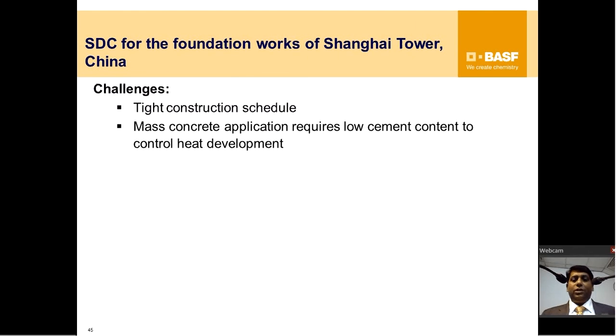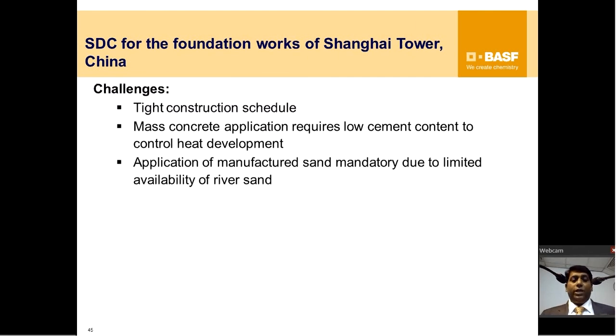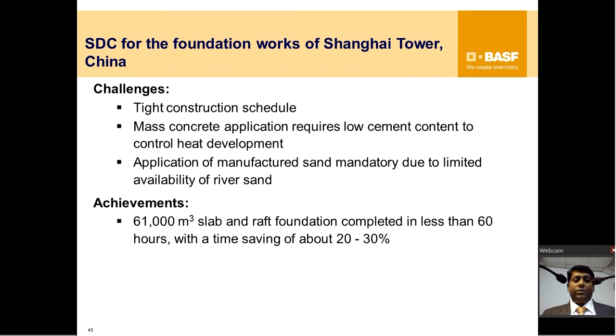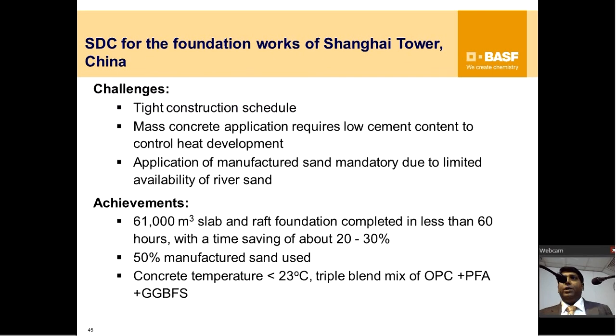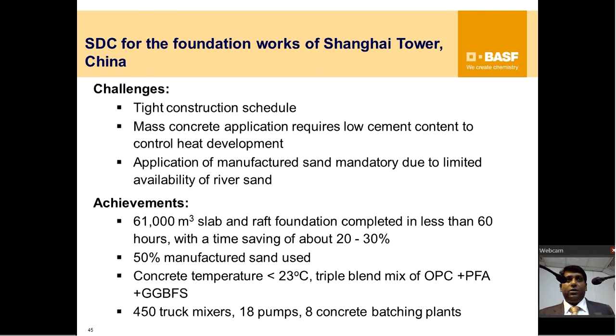Mass concrete application requires low cement content to control heat, and application of manufactured sand. The achievements were 61,000 cubic meters of slab and raft foundation completed in less than 60 hours, 20-30% savings in time just on a raft concrete pour. 50% manufactured sand was used. Concrete temperature was maintained at less than 23 degrees. Triple blend, OPC, fly ash and slag was used. The logistics: 450 truck mixers, 18 pumps and concrete delivered from 8 concrete batching plants. It was the logistics used to create this world record.